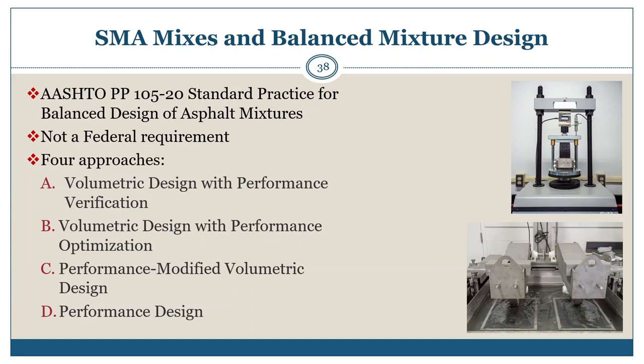Approach A requires full compliance with the existing volumetric requirements, but additional performance requirements, and is considered the most conservative approach. Approach B requires compliance with the existing volumetric requirements at the preliminary optimum binder content, but allows moderate changes in asphalt binder content for performance optimization based on mixture performance test results. Approach C allows some of the volumetric requirements to be relaxed or eliminated as long as the performance criteria are satisfied. It is considered a less conservative approach.